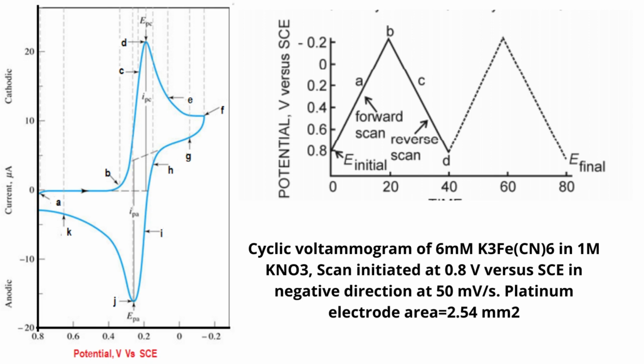The potential is still sufficiently negative to reduce, so the cathodic current continues, even though the potential is now scanning in the positive direction. When the electrode becomes a sufficiently strong oxidant, ferrocyanide which has been accumulating adjacent to the working electrode can now be oxidized by the electrode process, ferro to ferri. This causes anodic current, I to J. The anodic current rapidly increases until the surface concentration of ferrocyanide is diminished, resulting in the current peaking at J. The current then decays, J to K, as the solution around the electrode is depleted of ferrocyanide. The first cycle is completed when the potential reaches back to plus 0.80 volt.